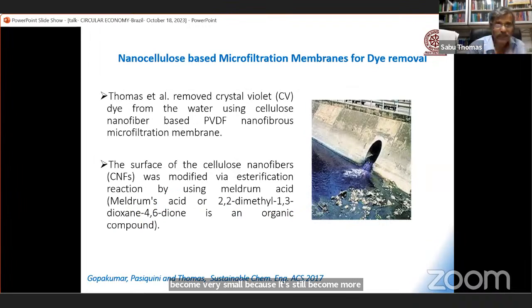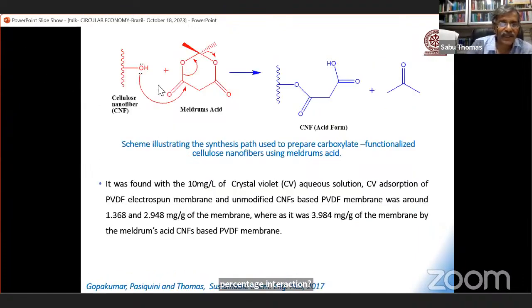One of the projects we have done is on crystal violet, a very important dye in the textile industry. But after dyeing, you see many rivers and water bodies are polluted by crystal violet. So in order to attract crystal violet by electrostatic interaction, we did some chemistry on the surface of nanocellulose. You can see this is nanocellulose. We reacted it with Meldrum's acid. Once you react with Meldrum's acid, you can introduce a CO minus group on the surface of nanocellulose.